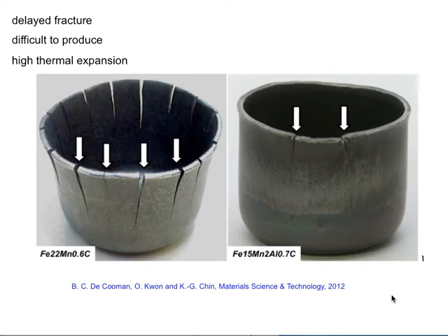And it's a problem not just in this context, but when we make extremely high strength bolts for bridges and so on, they break in an erratic manner unless you do something to control the hydrogen. I mentioned the mechanism by which we do that. We introduce tiny vanadium carbide particles which trap the hydrogen, in the context of bolts. So this is disastrous. If a car manufacturer sees something like that, they are not interested in this material.